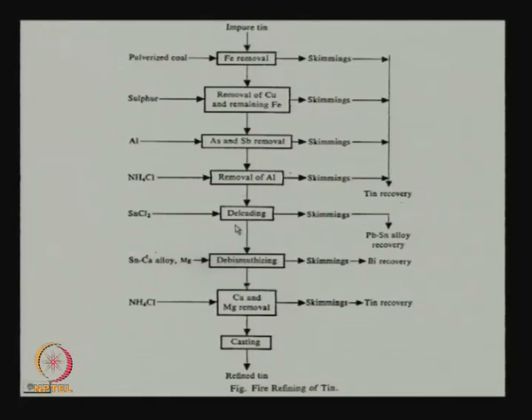We will have essentials for recovery of removing lead. The skimming will have lead-tin alloy, that will also go for recovery steps. Then we can add SnCa alloy, Mg to remove bismuth, skimmings go for bismuth recovery, again ammonium chloride goes for tin recovery, etc., etc. Finally, we get fire refined tin.